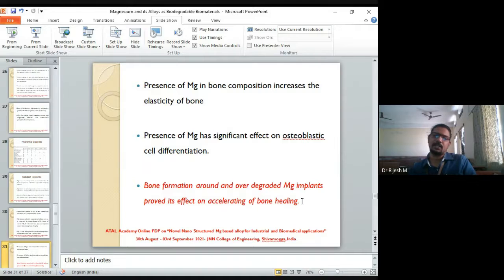Bone formation around and over degraded magnesium implants proves that it has an effect on accelerating bone healing. Got it. So when we did an in vivo experiment, we found that the bone formation in the vicinity of the magnesium implant is very good. Healing is all very good. That is because the magnesium implant liberates Mg2+. Got it. Due to this Mg2+, which has been absorbed by the bones in the vicinity, the healing happened to be very good, and that is one of the reasons why we call this a biodegradable implant.